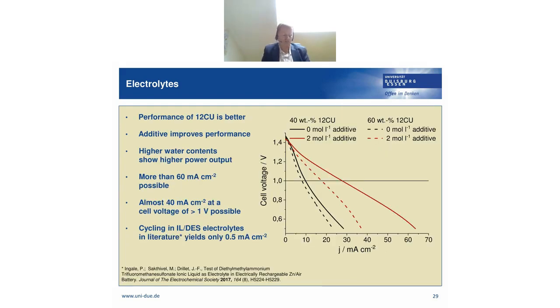So we did some performance tests. What did we test? We tested here, for example, a 40% mixture of 1 part choline chloride and 2 parts urea, so the rest is around 60% water. And then we have a 60% mixture of the 12CU, and this has, of course, 40% water. And some selected additives we added up to 2 moles per liter. And the additives really can improve the performance.